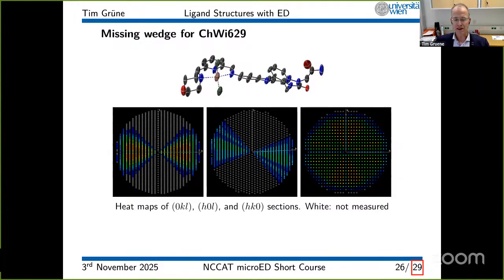If you do get high symmetry crystals, it helps, of course, because the symmetry covers the missing wedges. But if you have a crystal in a low symmetry space group, P1, P1 bar, you will always have a missing wedge from a single crystal. In order to compensate, you can collect data from various crystals, and it's good practice to collect data from as many crystals as possible. Typically 5 to 10 crystals are sufficient in order to get a decent completeness, even in a low symmetry space group. And I think that also applies to protein structures.